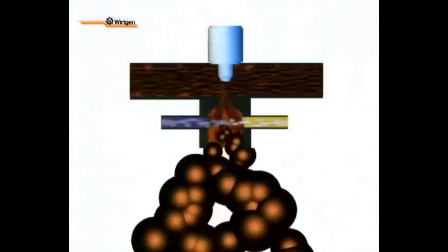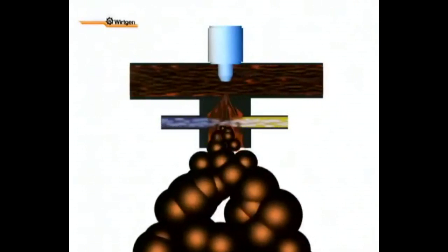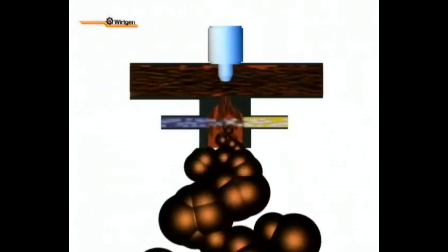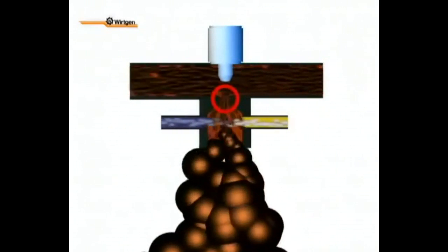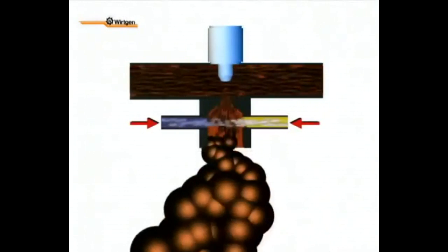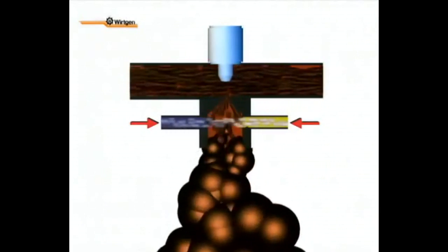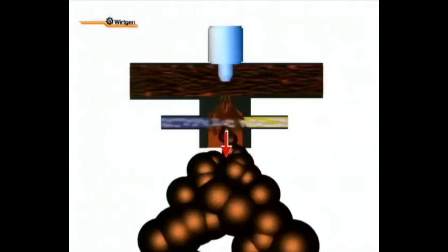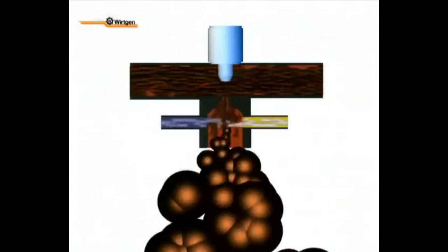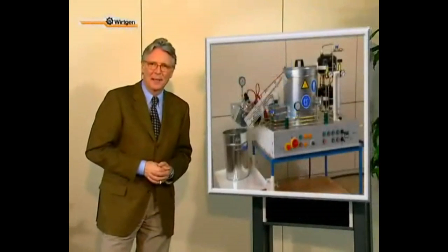This computer animation shows you what we cannot show you in reality: a view inside one of our spraying system's expansion chambers. The hot bitumen comes out of the pressure pipe via a nozzle into the expansion chamber. There, about 2% cold water and air are injected simultaneously. The bitumen foams explosively and shoots through the opening down into the mixing chamber. From the virtual world back to reality.